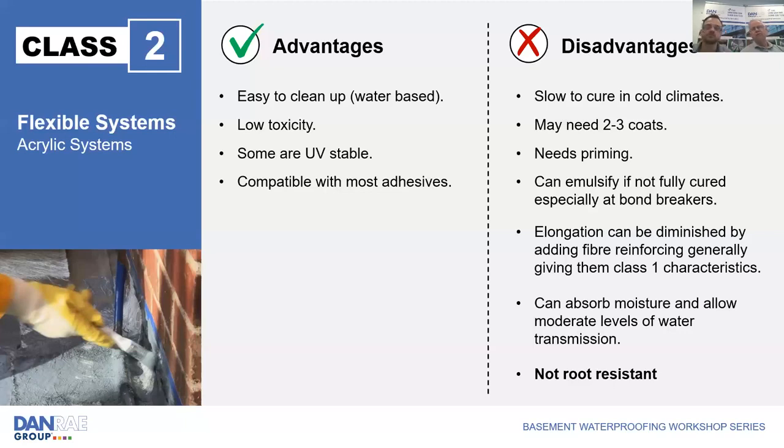No, that's pretty much what Daniel's covered. Sometimes you can get a bit of difficulty with moisture on the retaining walls and all that. So the water-based products tend to have a lot of issues. You may need to go to epoxy primers and everything. So generally, we tend to steer away from them. It's just too much mucking around, and there's a higher risk factor in using them. And one of the problems with a liquid is that you've got a variable application thickness as well. That's something the contractor has got to be aware of in applying a liquid membrane.